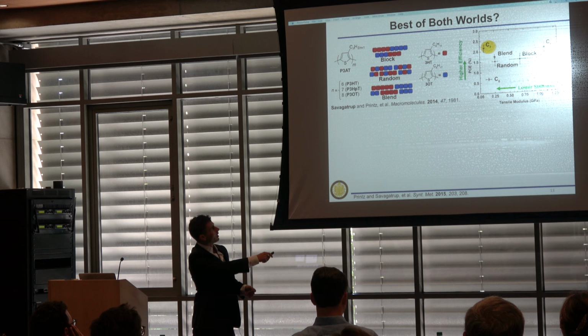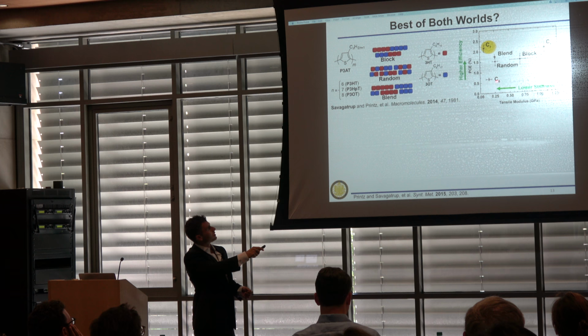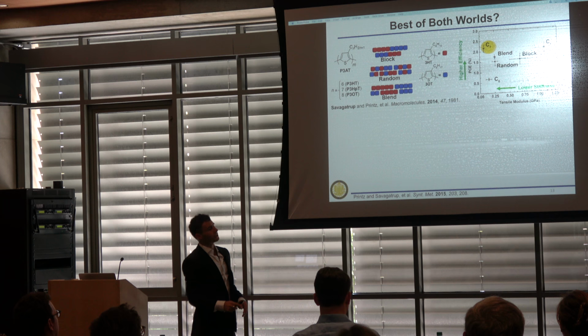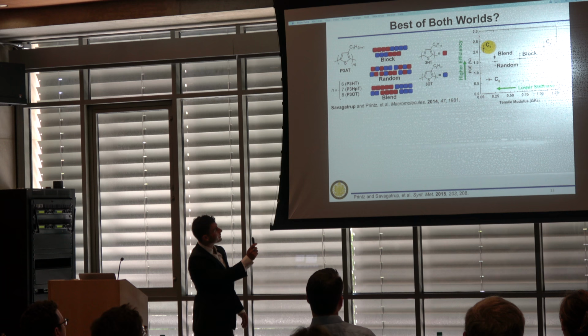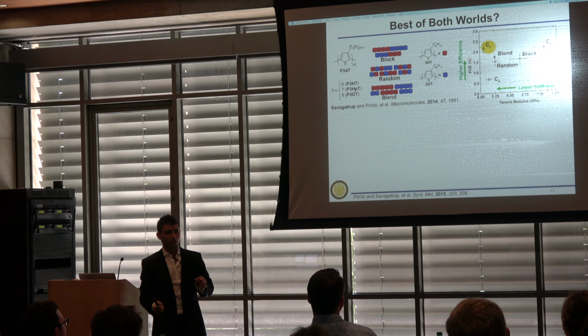And if we plot efficiency and tensile modulus, C8 is low efficiency, but also low stiffness, right? C6 is brittle, but highly efficient. And the other ones kind of seem to lie on a line in between. And then C7, lucky number 7, right, is in the favorable quadrant. It had high efficiency, like that of C6, but also stretchable and low stiffness, like C8. So if one is clever enough, you can co-engineer both of these properties into one material.